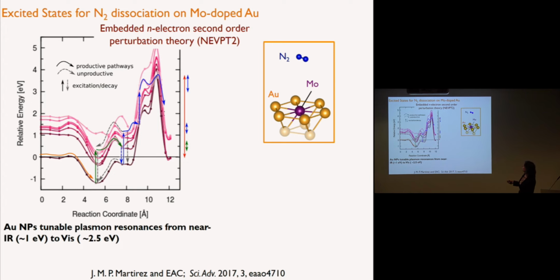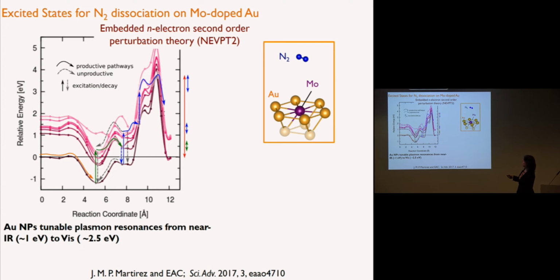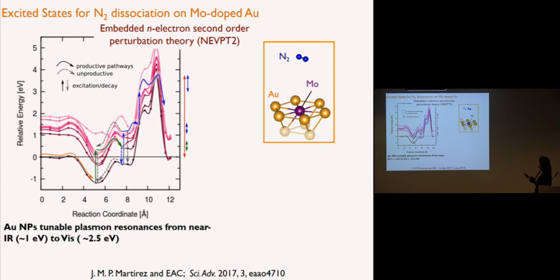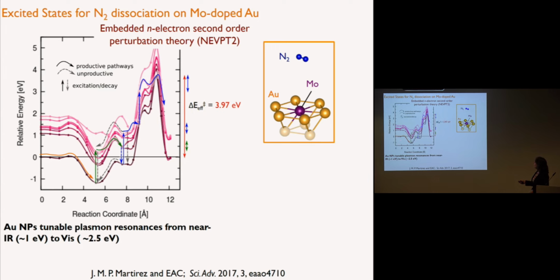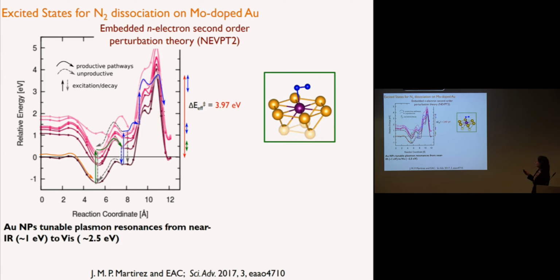And what you're seeing is this reduced reaction coordinate, and a whole set of excited states that we can calculate. What comes from this, and I'm going to lead you through this, is that initially what we calculate for the barrier for the ground state is 4 electron volts. So of course nothing is going to happen without the plasmonics. On the other hand, we can get adsorption. Here is the yellow arrow showing you that you can get adsorption with essentially no barrier of nitrogen on the molybdenum, but then there's a barrier to come back, and then there's a huge barrier to overcome to break the bond. So what we suggested is that what's going to happen, in green, is that you can use these gold nanoparticles, which have tunable resonances that go from the IR to the visible, 1 electron volt to 2.5.